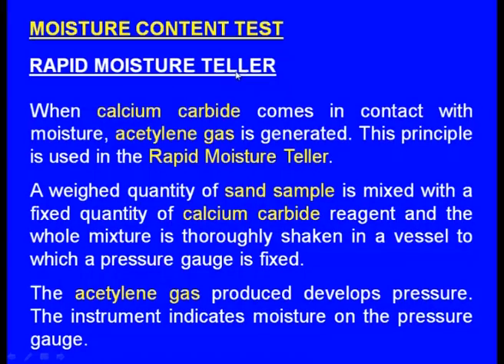Recently, a new technique has been developed — that is the rapid moisture teller. The infrared oven process takes about 10 minutes totally, whereas this rapid moisture teller tells us the result within a minute. When calcium carbide comes in contact with moisture, acetylene gas is generated. This principle is used in the rapid moisture teller.